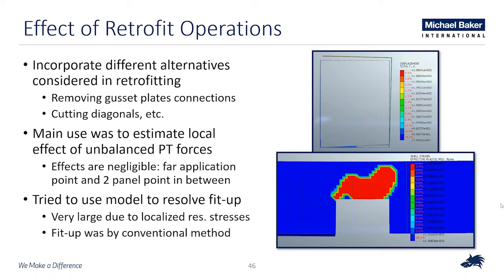However, when the steel workers go out there to square this through conventional methods, they can apply a variety of restraints that are difficult to actually model closely in FEA NX, but that are sufficient to close it. So in this case, the way we looked at this in the model wasn't really how the repair procedure went, because with conventional methods that they use for feed up, basically just conventional chain and some hoisting, they were able to close the gap to within a working tolerance, because that's the other part in our model. You're trying to deform and square this section to make it perfectly square, whereas in reality you are fine working with a little bit of tolerance, and in this case it makes quite a bit of difference in terms of the forces necessary.